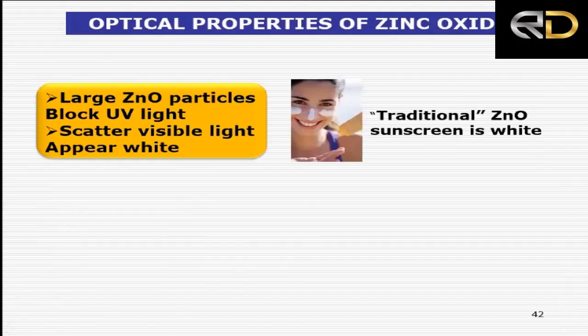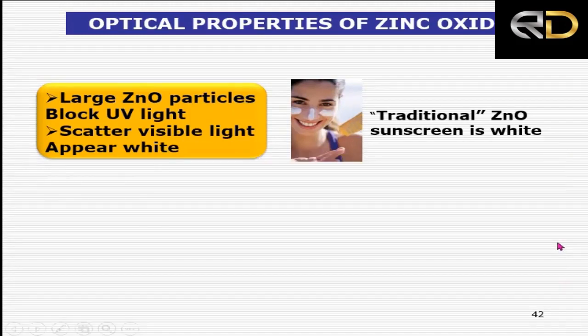Now, you know that 5 or 10 years before, cricketers used to use white paint on their faces so that there is no etching from the UV radiation, and that was nothing but zinc oxide powder, macro-sized. Zinc oxide blocked the UV radiation, but now you don't see the faces white because nanosized zinc oxide is being used for coating the faces, and they hinder the passage of UV radiation, but they appear to be transparent.